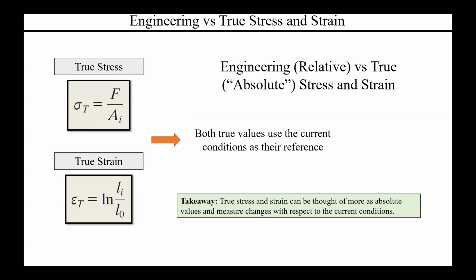So in the case of true stress, it's still the same definition, right? Stress is force per area, but specifically the area is now the area at snapshot i, so a point in time rather than the initial. So this allows you to have a better estimate of what the current area of your cross section is, or whatever plane of the material where the force is actually being applied. And true strain is still kind of with respect to the reference. You do have that relative value of current with respect to reference, but now it's a log-based relationship rather than just a basic linear relationship.